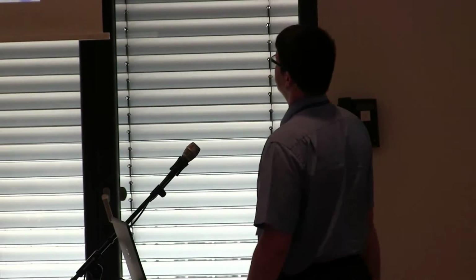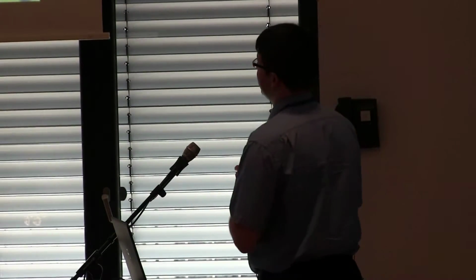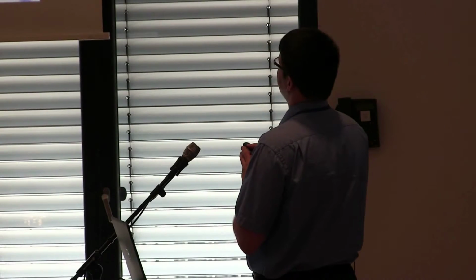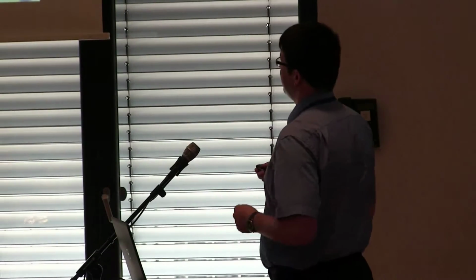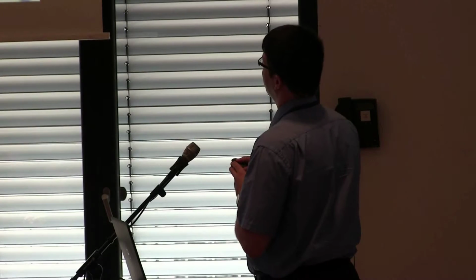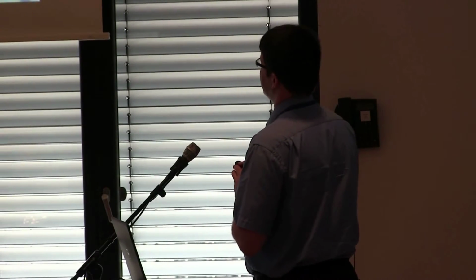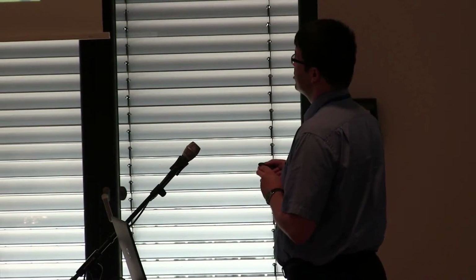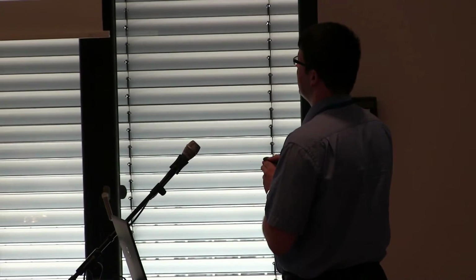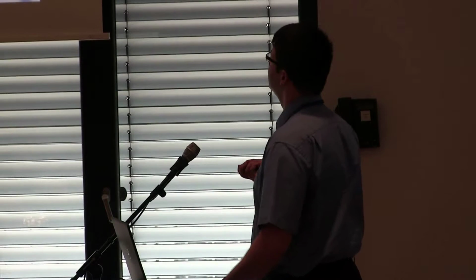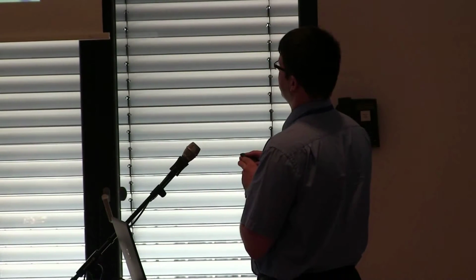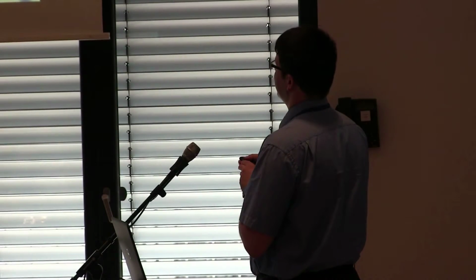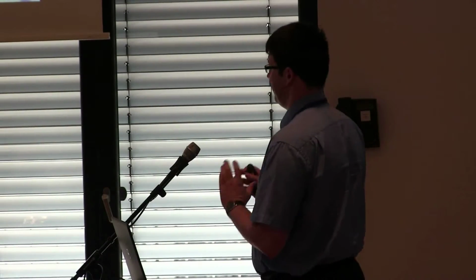So we extended the study to other organisms and cells. We took some fibroblasts, and we also took bacteria like S. aureus, and we also observed how the toxicity of the alloy nanoparticle changes. Here two things are plotted: first the minimum inhibitory concentration and the toxic concentration, while of course a lower inhibitory concentration means a higher toxicity. First you can see that the silver particles are much more toxic than the 50-50 composition.